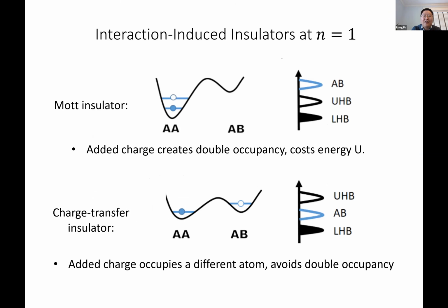Okay, so now let us consider increasing the filling to n equals 1, when we have one charge per unit cell on the honeycomb lattice. In this case, obviously the charge should go occupy the anion sites. So we have one charge per anion site, right? This corresponds to the local AA stacking region.